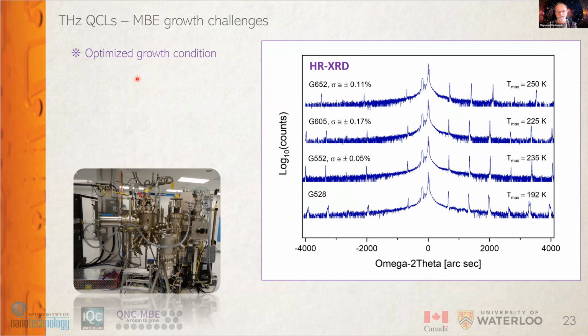Of course, optimization of the growth conditions is the key. We have been in it for more than a decade, so it's 15 years we managed to cover quite a bit of ground there. The big graph on the right hand side shows those hero lasers at 250K operating temperature, and those are the high resolution XRD scans, and those sharp peaks here are just signatures of our superlattice. In order to get these lasers going, you need well over 200 repeats. Those are very thick structures.